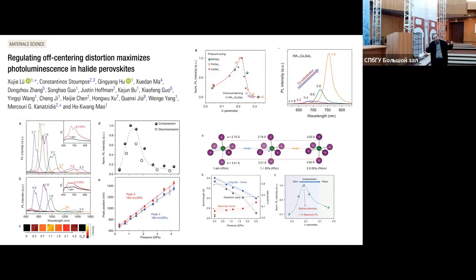after you apply pressure to an extent, you start having the material shine light. And inspired by the high pressure experiments, we did also the chemical pressure experiment. Namely, we substituted cesium for methylammonium throughout the series. And while cesium emits very strongly at its bandgap, methylammonium doesn't, we can fine-tune it continuously by triggering the photoluminescent threshold. And we found that there is a special rate for a special separation for the octahedra and the pyramids, so that we can trigger photoluminescence to appear.